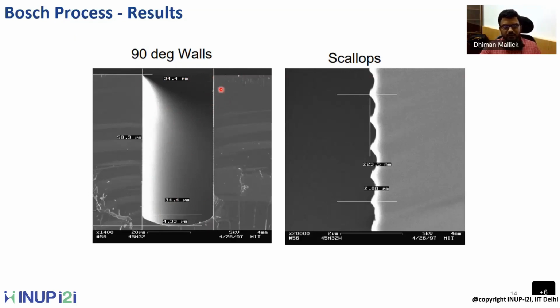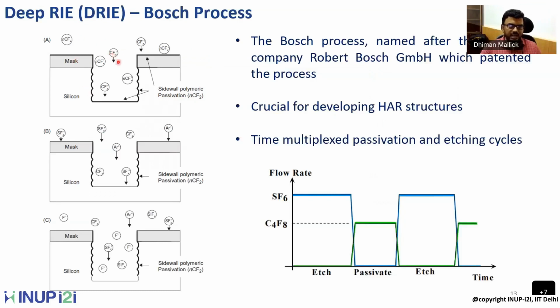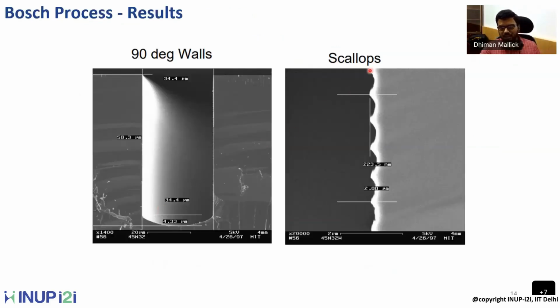So if you now take a very zoomed look at these side walls, what we can see is that it's not actually very uniform. Rather, there are very small-sized wavy structures, which are called the scallops, that are created. So why is it created? We said that in the case of DRIE, we have this passivation step where you passivate the side walls using some sort of a polymer. Now, when the next step of etching is happening, it is obviously unable to etch the side walls significantly, but still there is some minimum amount of etching going on. Because of that, this kind of scallop layers are created in multiple cycles of this DRIE process.